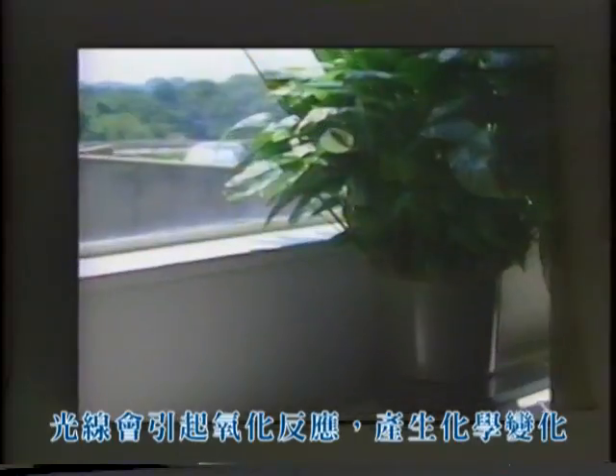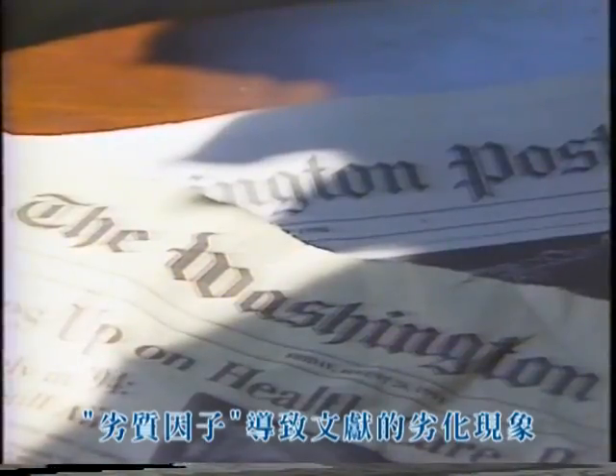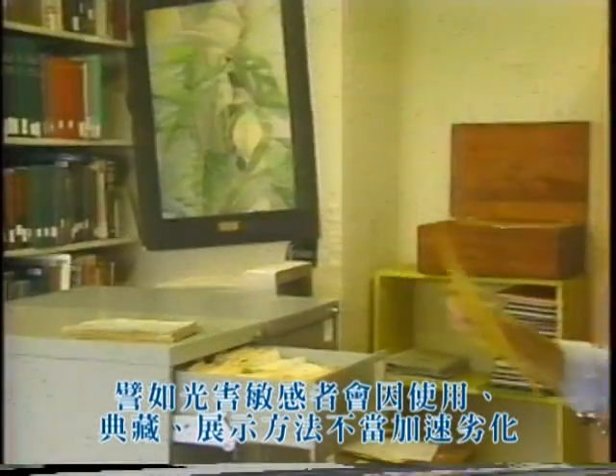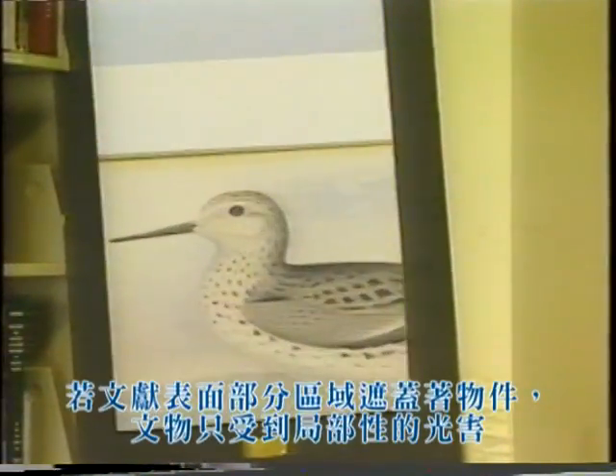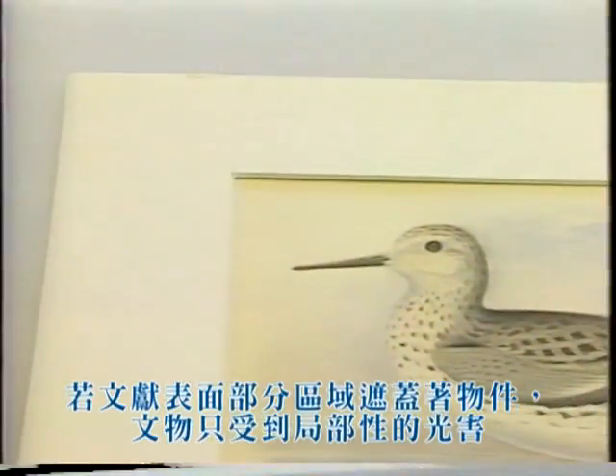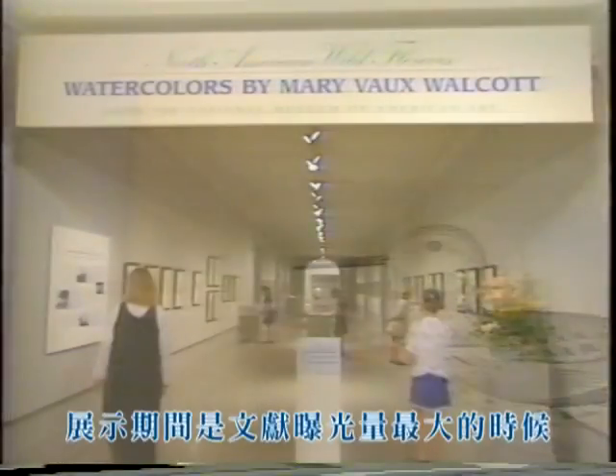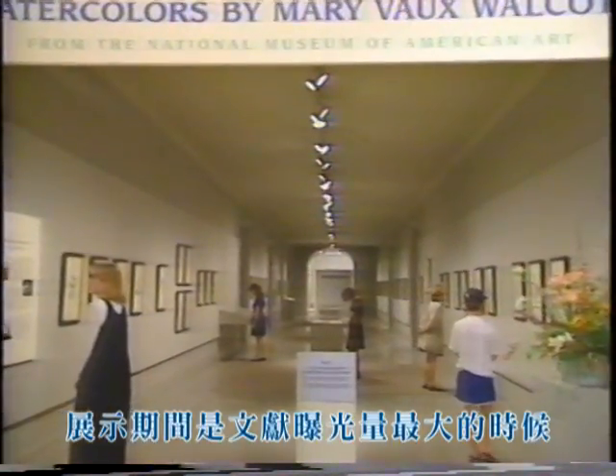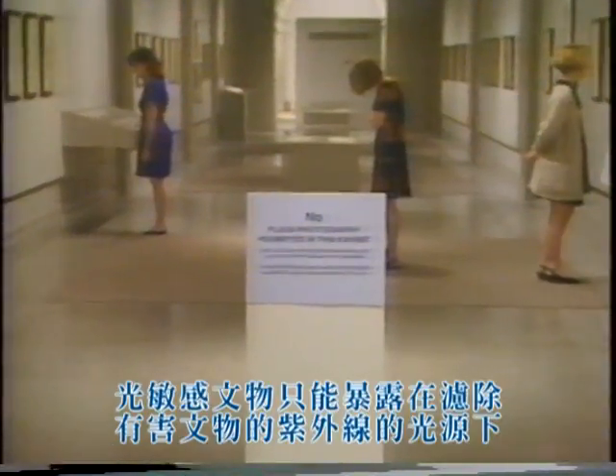Light can cause oxidation, which leads to chemical changes that can fade or darken some types of paper and media and make paper very brittle. Document deterioration caused by inherent vice, such as sensitivity to light, can be accelerated by incorrect use, storage, and display. Only part of a document might be affected by the light if the document is partially covered by items laid on top of it. This is especially obvious in documents that have been matted. Display or exhibition of paper materials results in most of the excessive exposure to light that documents receive. Sensitive items should only be exposed to light that is filtered to block harmful ultraviolet radiation. Even then, light levels should be low and the documents exposed for only short periods of time.